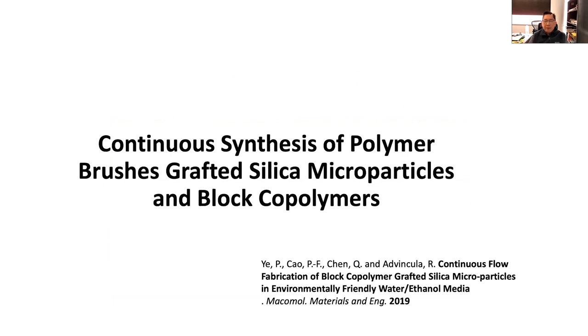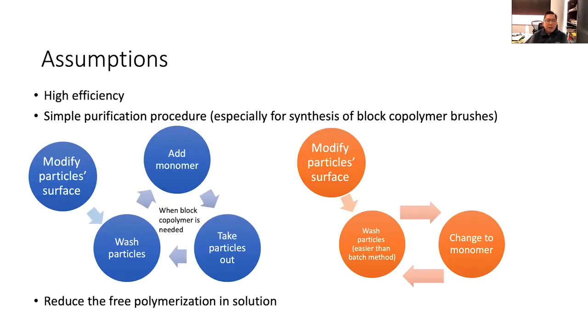In another paper that we published back in 2019, this involved the grafting of polymers on silica microparticles and the demonstration that we can make block copolymers. This involves modifying the particle surface, attaching the chain transfer agent on the surface, washing the particles with a solvent, adding the monomer, taking the particles out. Well, now, what I'm referring to is a traditional method of reacting or producing these core shell particles in a flask. However, we can simplify things in a continuous flow reaction by first modifying the particles on the surface, washing the particles, introducing the monomer, changing the monomer back and forth if we want to, but then there's no more taking the particles out of the reactor. In other words, the whole reaction can be done under flow.